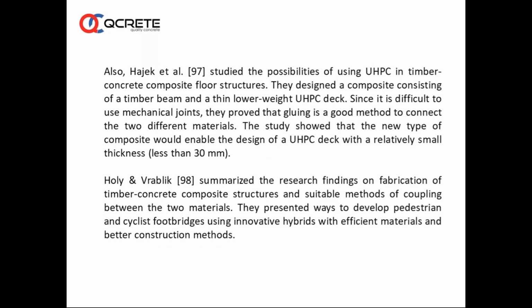Some people also studied the possibilities of using UHPC in timber concrete composite floor structures. They designed a composite consisting of a timber beam and a thin, lower weight UHPC deck. Since it is difficult to use mechanical joints, they proved that gluing is a good method to connect the two different materials. The study showed that the new type of composite would enable the design of a UHPC deck with a relatively small thickness.